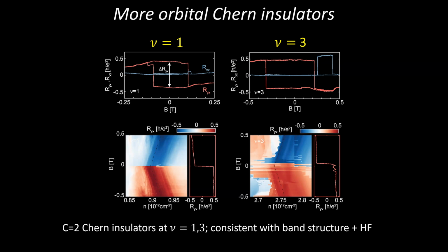So it reproduces the physics, but there's one funny feature that occurs if you look at 3 electrons per unit cell. It's some detail question why this happens at 3 but not at 1. But when we first looked at this data, we thought, there's a cable loose, why is this switching back and forth? What you're doing is you're varying the charge carrier density by an electric gate, and then you're varying the magnetic field and you're switching it back and forth, and nothing seemed to stay at the same value.